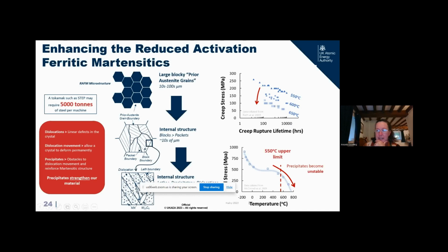And you can see here that as we take the temperature up, the creep performance over creep lifetime is reduced. And this work is from Michael Rieth, one of the foremost scientists in fusion metals in the Eurofusion program in Europe. And you can see the rapid drop off here at the moment above 550, where the existing precipitates are becoming unstable, and therefore we cannot at the moment take our Eurofer beyond 550.